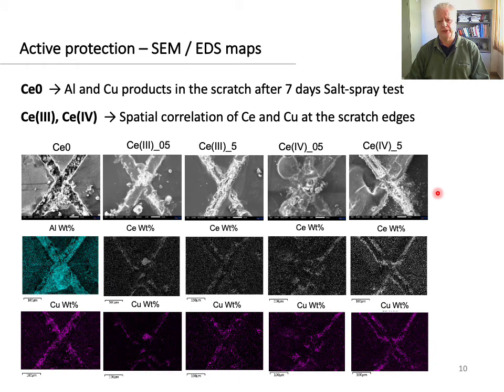Now, to study the regeneration mechanism, SEM images and elemental EDS maps of the scratched coatings were obtained. Compared with the reference sample, the SEM images show that the cerium-containing coatings form a film in the scratch track. EDS maps show that the central region of the scratch track is mainly composed of aluminum corrosion products. Although cerium was not detected in the central region of the scratch due to the high sample depth of EDS, a clear spatial correlation between cerium and copper-rich zones in the scratch track edges can be observed, more evident here for the